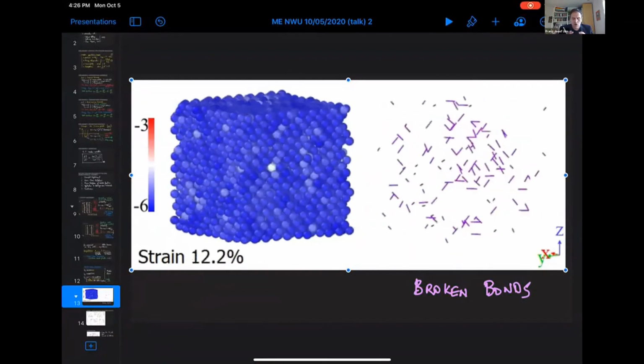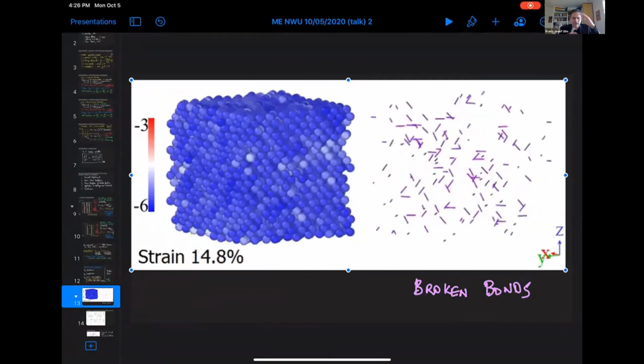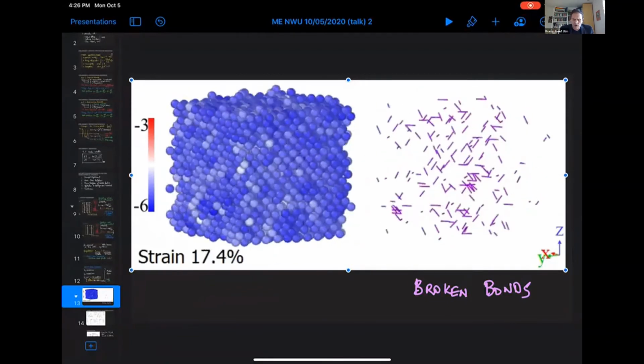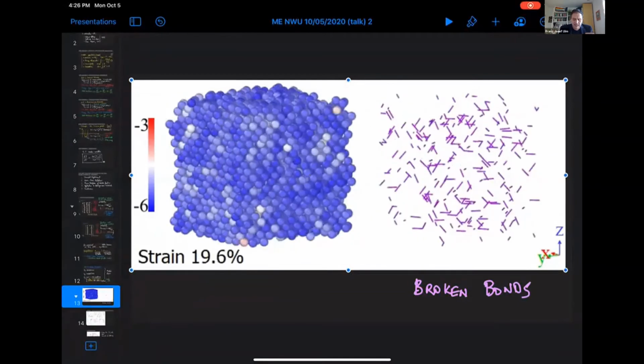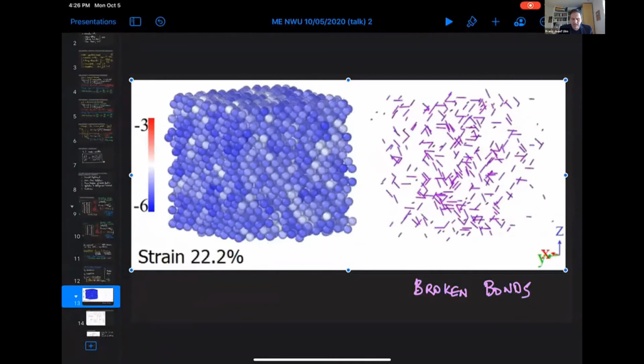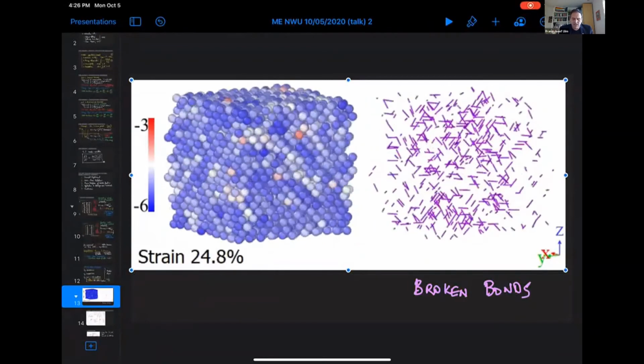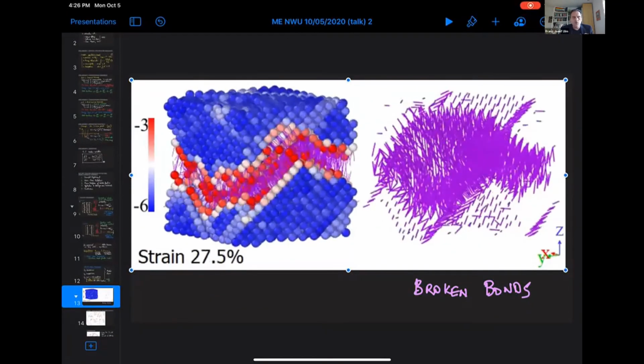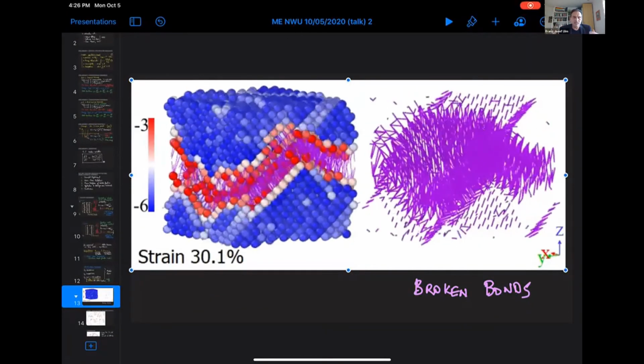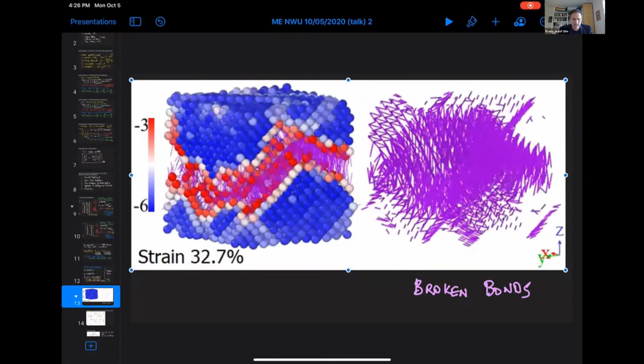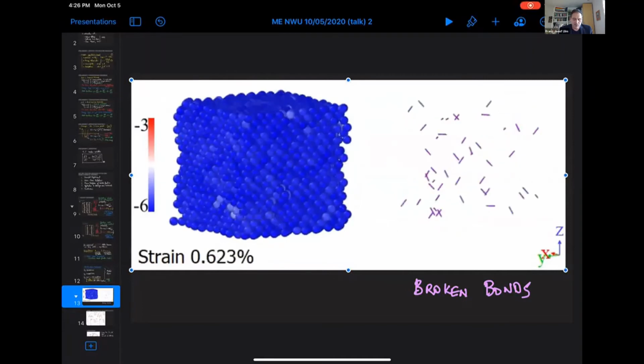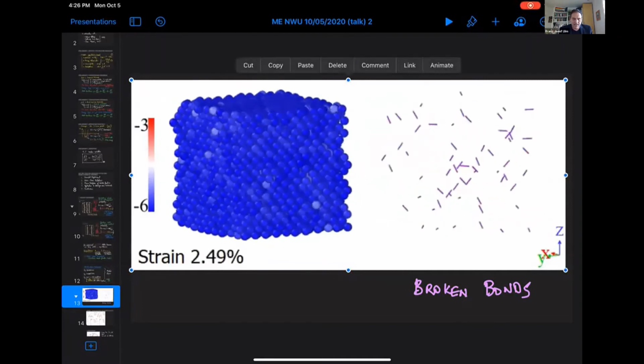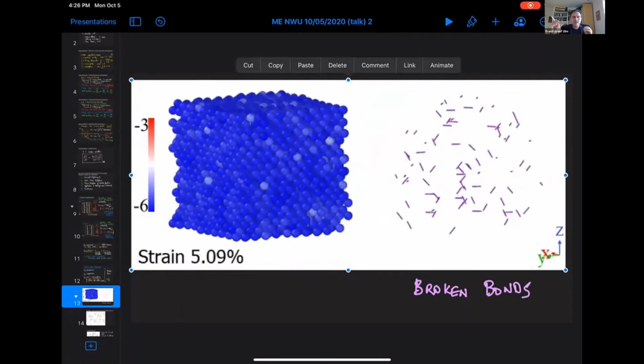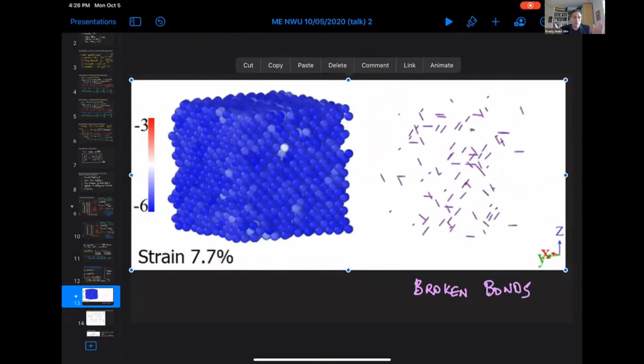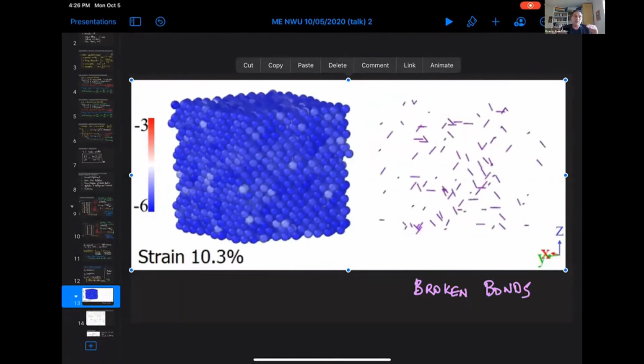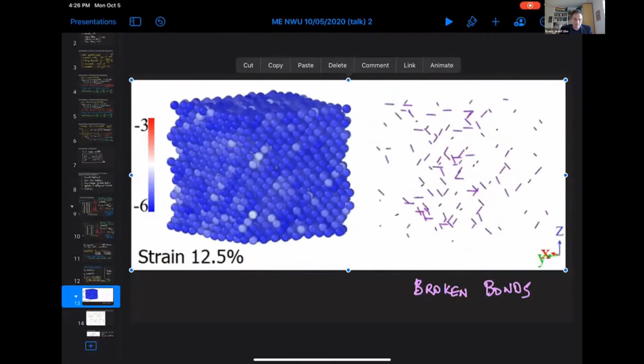And you see under this homogeneous loading, it's a hydrostatic, actually a hydrotension experiment with the same strains applied in all directions. At each step, there's no history because we're only looking at equilibrium. You see that the density of cracks, or bond breakage, increases until you form these crack patterns in the system. The color coding here refers to the energy. So if you allow me to play it again. You basically keep on probing from the outside for a given delta mu, you probe all bonds, and then you find the equilibrium when the probability of deletion or insertion becomes the same.